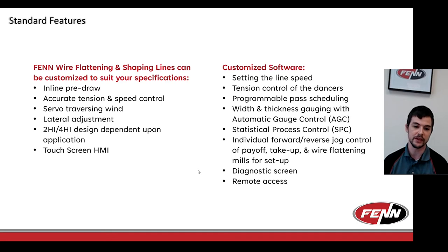And the next point addresses the biggest difference you'll see when we're talking about the rolling mills in general. Other than what I alluded to on typical size and journal, the biggest difference between a strip mill and a wire mill is that on wire mills we put a lateral adjustment frame. The purpose of that is that your wire width is obviously usually significantly narrower than your strip, and relatively speaking, to the size of the roll and everything it's being worked with, is not that large. So we usually give you a roll face that's significantly wider than the face of the wire.